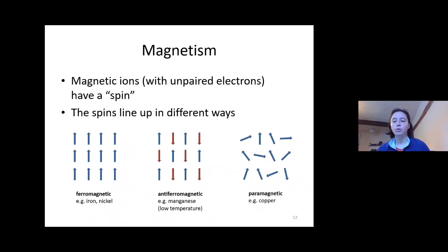As we cool down, we'll get less and less thermal energy. The spins move less and less, and they'll probably settle into one of these two arrangements. So on the left is a ferromagnet where all the spins like to be aligned parallel to all of their neighbours. And that's what you think of as a magnet. Things like iron and nickel, where they've got a permanent magnetism, all pointing in one direction. Another option is an antiferromagnet, where each spin likes to point in the opposite way to its neighbours. So we get this kind of chessboard arrangement. And the choice of ferro or antiferromagnetic will depend on the exact atoms that are involved.